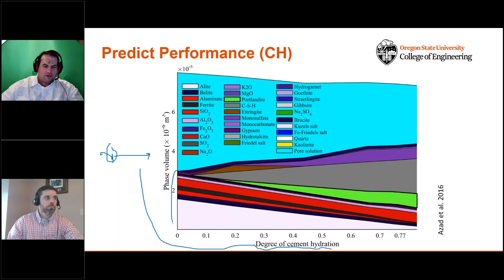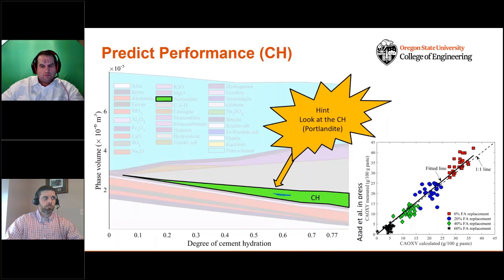So the bottom part of this at 0% reaction is our cement and fly ash. The top part of this is simply water. As we move across from left to right on this plot, what we notice are the reaction phases that are happening. We get CSH forming, that's kind of good, right? We get some monosulfate forming. We can get some ettringite forming, right? We can even get some portlandite, or calcium hydroxide, forming. So now we're able to use the fundamental chemistry of the system. Give us the chemical composition of the fly ash, the chemical composition of the cement, and the volumes that we're using in that mixture, and we can start to predict the calcium hydroxide, and that's what we've been doing in this model over here.